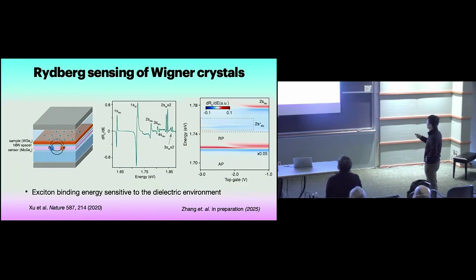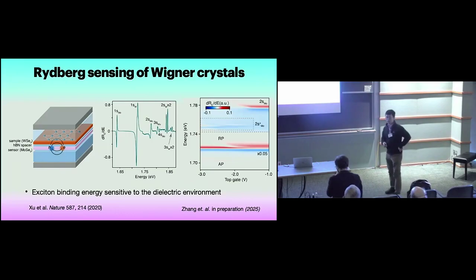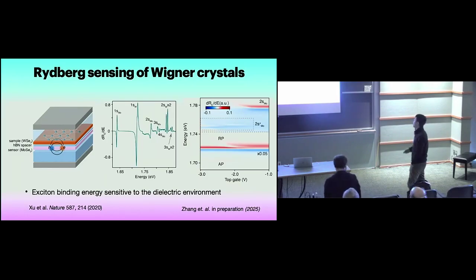So we know that over this range, in the middle, we are in the Wigner crystal phase. So this is the 2s exciton, and it has some energy. But when you go to the electron liquid phase, there is suddenly a redshift of the exciton energy. This is because when you go to the electron liquid phase, there is more screening of your Coulomb attraction. So the binding energy of this electron-hole pair is reduced a little bit. Because the 1s exciton, which I didn't show, doesn't change, this redshift corresponds to a slight reduction in the binding energy of the exciton.